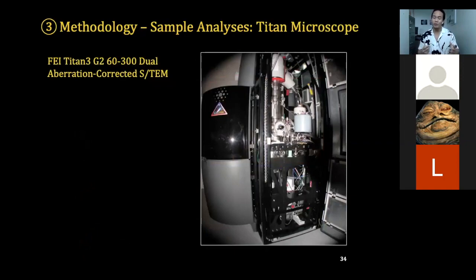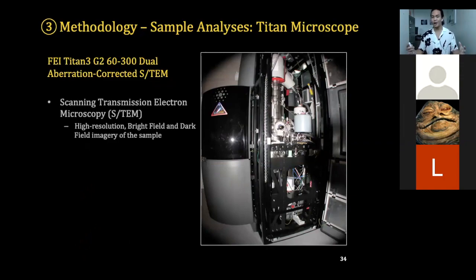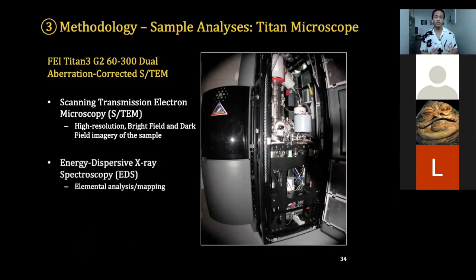The next instrument where we put the double tilt holder is the FEI Titan 3 G2 60 to 300 dual aberration corrected scanning transmission electron microscope, or Titan microscope for short. So again, what STEM can do is give us high resolution bright field and dark field imagery of the thin section that we just created. We can also perform EDS, which is similar to what we did with the FIB. However, this time we're looking at several sections in the thin section as opposed to just the surface of the sample. And finally, we can also perform selected area electron diffraction, which gives us patterns where we can analyze and figure out the crystal structure of our sample.